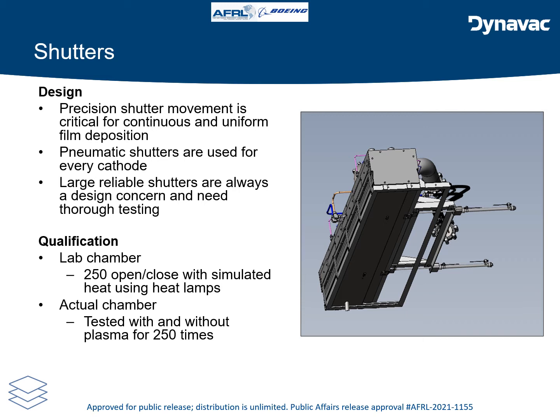Large reliable shutters are always a design concern in these kind of chambers, mainly because of 2 reasons. One, the shutters tend to get hot and they tend to get accumulated with a lot of sputtered material because of the burn-in cycles. Hence, a thorough analysis was done in the design phase and experimentally verified during the testing phase. During qualification, we did about 250 open-close cycles in the R&D lab chamber at Dynavac with simulated heat using heat lamps, and we repeated the test in the actual chamber with plasma.